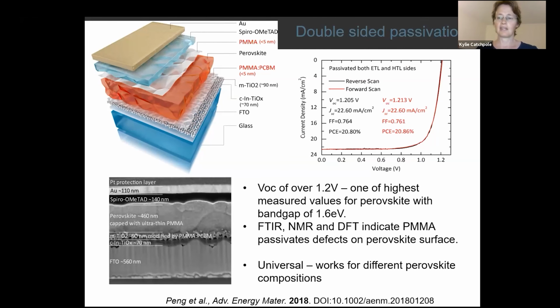So this was at the interface of the spiro layer and the perovskite. We're able to get a high voltage for that. And what we found is that the PMMA provides passivation of defects on the perovskite surface. So this was via a combination of FTIR, NMR, and DFT. And overall, that allowed us to conclude that the PMMA was passivating defects on the perovskite surface.